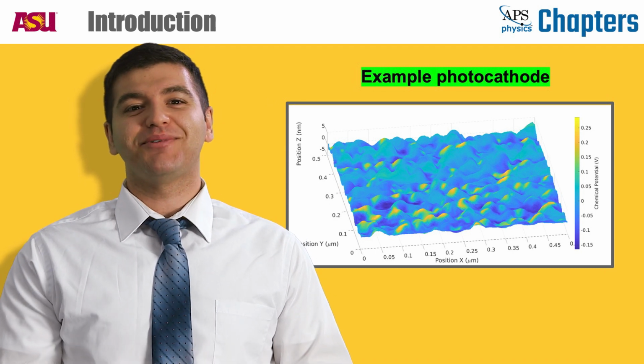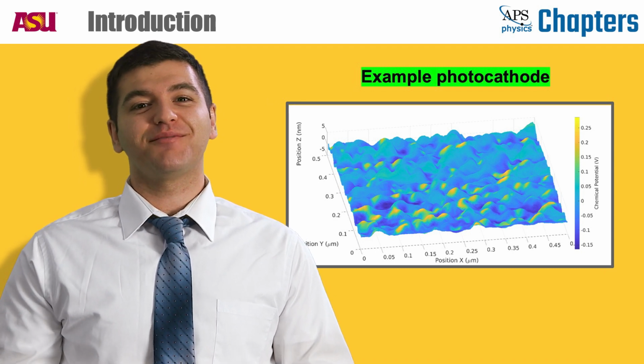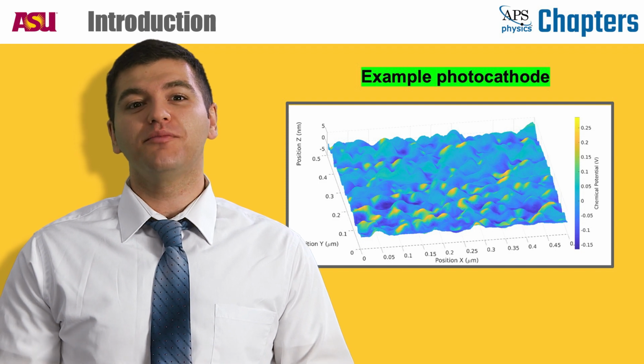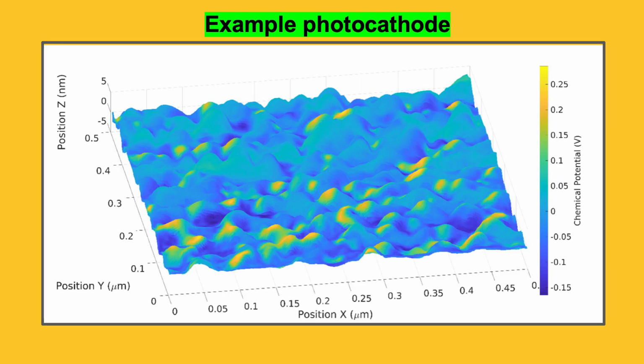Here, I show an example of a photocathode measured on the atomic force microscope and Kelvin probe force microscope in our lab. The axes show the spatial scale, XYZ in nanometers, and the color map shows the work function variation in volts. I wrote a particle tracking code to compute the contribution of roughness on MTE from real photocathode surfaces like the one you see here.